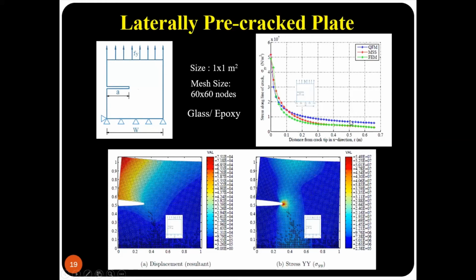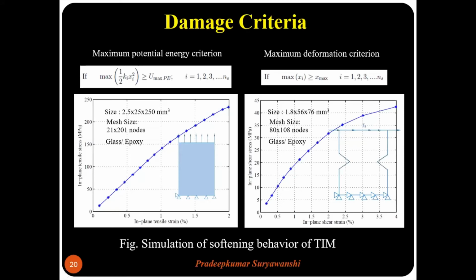Now, as I mentioned during the flow chart, I will explain our damage model. So here we propose two damage criteria for our MSS model, that is maximum potential energy criterion and maximum deformation criteria. In maximum potential energy criteria, we consider that if maximum of potential energy, that is 1/2 kx square of any ith spring is greater than the allowable maximum potential energy. This is determined deterministically or by using Weibull function. Okay, but we did it by using some experimental insights. Okay, so we set some maximum value of potential energy for that particular simulation, and if any of the springs crosses that particular value, then we say that that spring is damaged, and we assign the stiffness of that spring to 0 so that it is removed from the mesh.